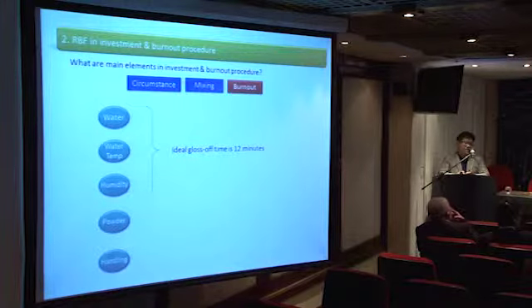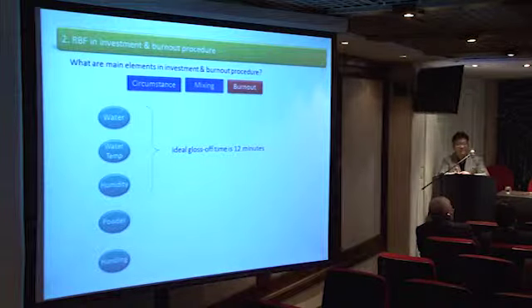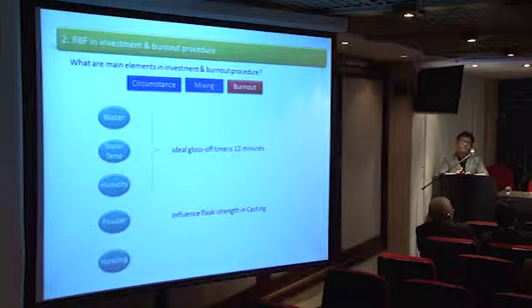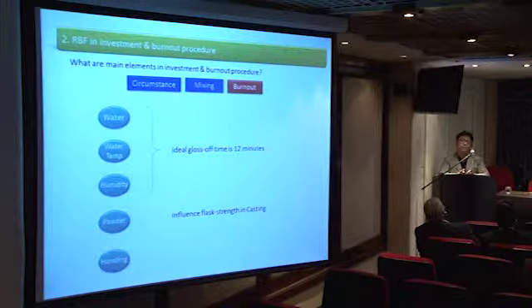When we mix, please calculate your gloss-off time as well as your parameters. For most gold and silver investment, the ideal gloss-off time will be about 12 minutes. If it exceeds or if it goes faster, please consider that you'll have some kind of casting defect. And also, the handling of the powder as well as the mixing process of the powder will influence a lot the strength in casting.